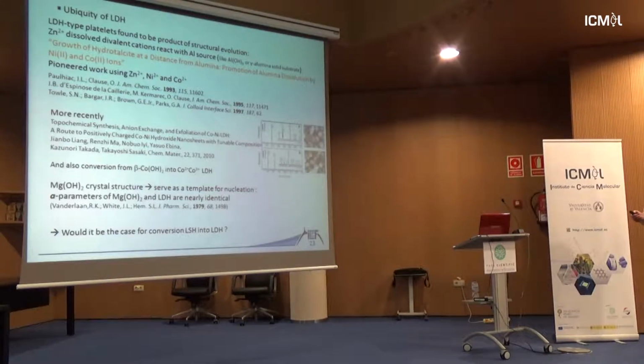I will go very quickly over this long slide, just to show you that we didn't invent everything. It was present in the literature quite a long time ago that LDH can be formed on the surface of magnesium hydroxide, and can form on the surface of aluminum, because of the ubiquity of LDH. If you have a good pH, and it's quite a large value, you can yield LDH at the end of a reaction just on the surface of a metal if you add some aluminum hydroxide, for instance, or some nickel or cobalt. And the final product, passivating the metal surface, will be LDH. And the same for lithium aluminium.